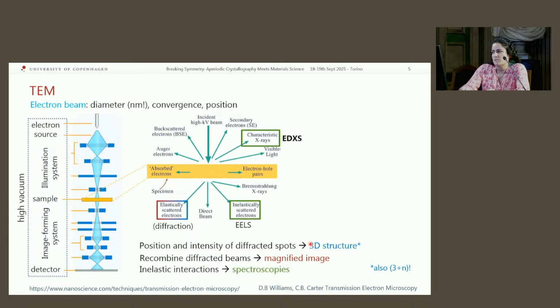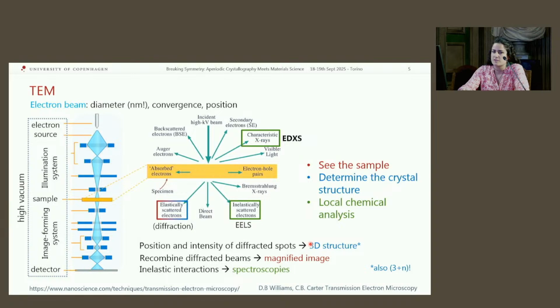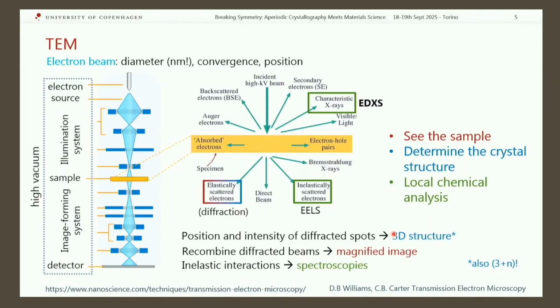Then we can also look at some of the inelastic interactions. For example, when the electron beam is partially absorbed and some excess energy is emitted, the sample can emit X-ray fluorescence, and we can then do energy dispersive X-ray spectroscopy. So, in short, with the transmission electron microscope, we can see the sample, we can determine the three-dimensional crystal structure, and we can also do local chemical analysis. So all these analyses are on the very same spot of our sample, whereas otherwise I would need 3 different instruments.